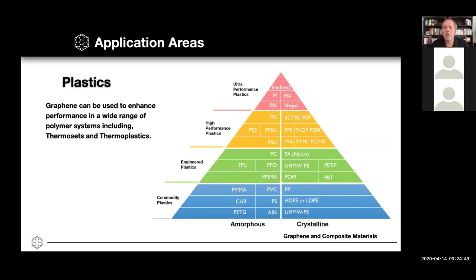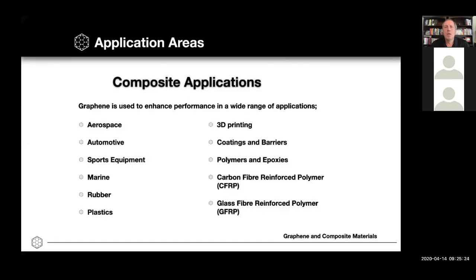For example, a very common material like PA nylon, we've seen multiple companies getting 300 to 400% improvement in strength and modulus by adding a very small amount of graphene to the material, which then enables you to use some of these materials in new application areas where before they weren't up to the performance specs. So that's an interesting aspect. It's a way of perhaps reducing cost or using a more manageable material.